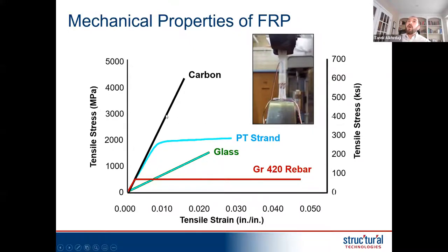If I look now at carbon, you can see it here, the line in black, it's linear elastic. You can see the slope of the line represents the stiffness of the material, the modulus of elasticity. And you can see here it's almost as stiff. This is carbon fiber, the fiber, not the composite. It's as stiff as steel, and sometimes we have products that are actually 1.5 times stiffer than steel, but they are linear elastic and they go all the way to failure and then they snap.